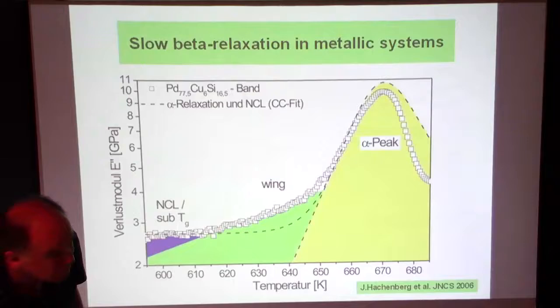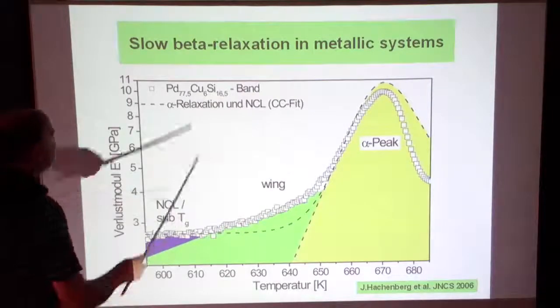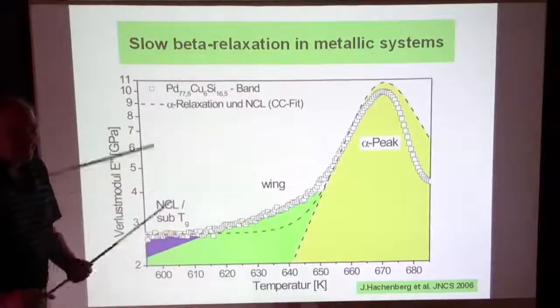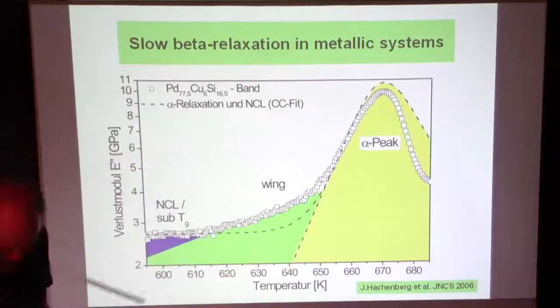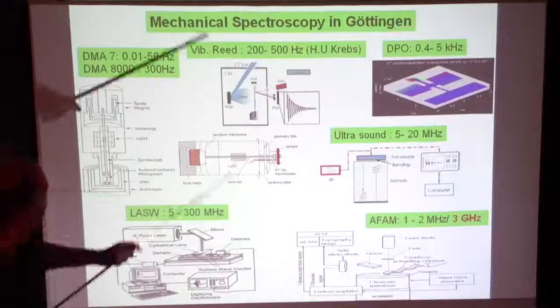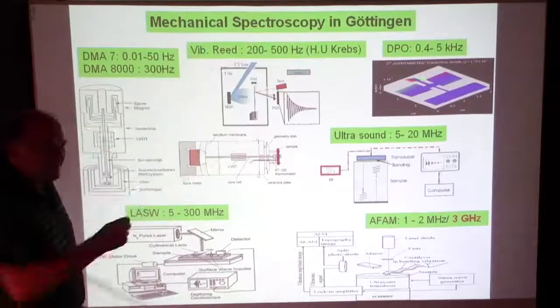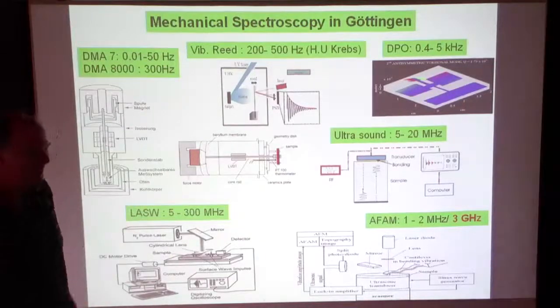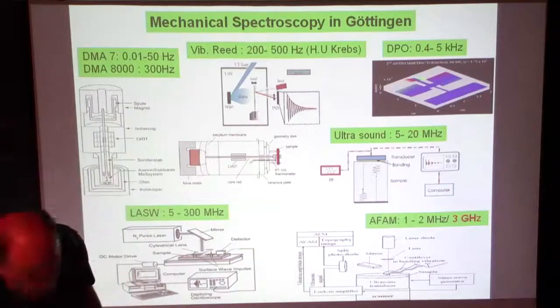I mean, the dielectric constant for a metal should have worked, right? Yeah, that's why we measure mechanically. This is just mechanically. That's the reason, because otherwise we wouldn't see anything, right? So we always use mechanical excitation to avoid this problem. Although it's a bad metal.